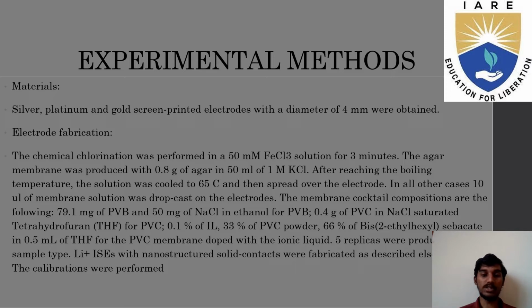The membrane cocktail compositions are the following: 79.1 mg of PVB and 50 mg of NaCl in ethanol for PVB, 0.4 grams of PVC in NaCl saturated tetrahydrofuran for PVC, 0.1% of IL and 33% of PVC powder, 66% of bis(2-ethylhexyl) sebacate in 0.5 ml of THF for the PVC membrane doped with ionic liquid. 5 replicas were produced per sample type. Li+ ISEs with nanostructured solid contacts were fabricated as described elsewhere. The calibrations were performed by subsequent LiCl additions.